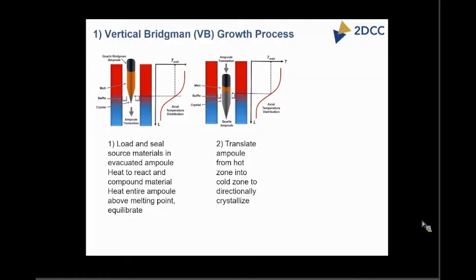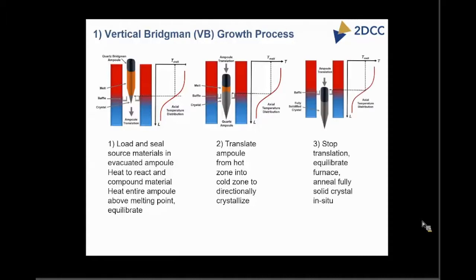And then upon the completion of the translation, when everything is below the melting point, you stop, equilibrate the furnace, try and set up a uniform temperature profile, typically do some sort of in situ annealing of the crystal, looking at trying to anneal out possibly interstitial vacancy defects, reducing stress in the crystal, etc. And then it can be unloaded from there.